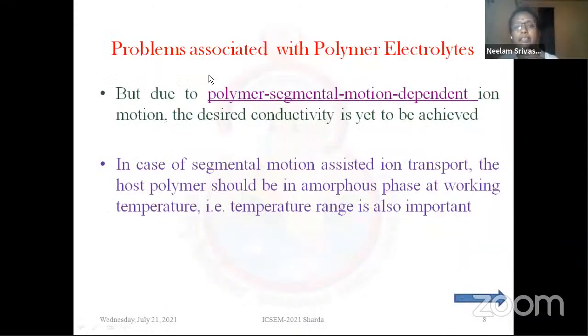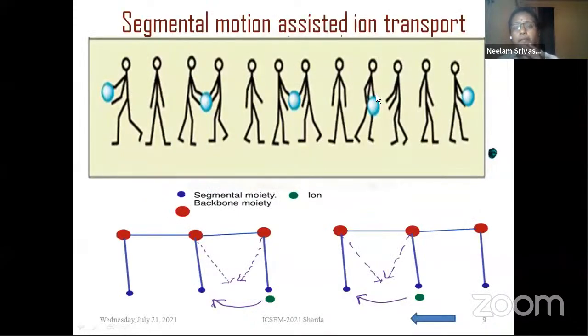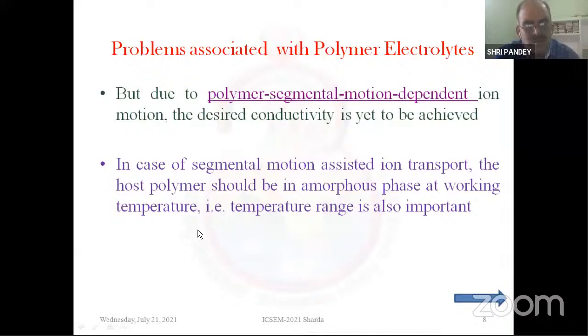So why this problem is associated with the polymer electrolyte is that in polymer electrolytes, the ion transport comes through the segmental motion. This is a very typical picture of the segmental motion, where if we consider these sketches as the polymer backbone, then you can see that the side chains are moving and transferring the ions from one place to the other. And the same is shown in the lower figure also, how the segmental branches move. This green color ion, if the green color represents the ion, moves from one branch to the other branch. Because the segments of the polymer are quite heavy, their movement is quite slow,